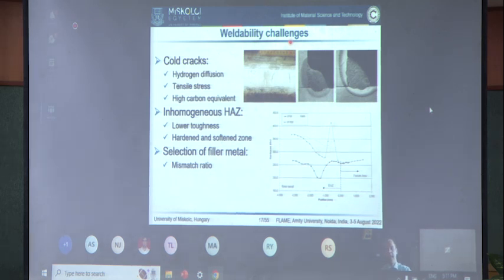This slide summarizes the weldability challenges of high-strength steels. The first topic is the higher cold cracking sensitivity. Cold cracking can be caused by the combination of hydrogen diffusion, tensile stress, and high carbon equivalent, so brittle martensitic base material. These kinds of cracks can occur in the heat affected zone, as you can see in these fillet welds, but they can also occur in the middle of the weld.